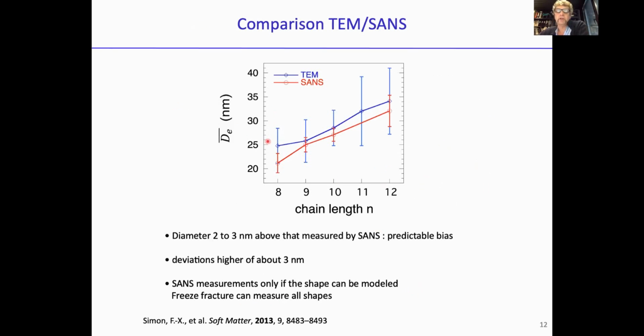So the blue curves represent what I've shown you. These are the diameters as measured by the freeze fracture, and you can see here the polydispersity. And you can see here the real measurements done by small angle neutron scattering. So the first observation that you can make is that the diameter measured by electron microscopy is 2 to 3 nanometers higher than those measured by SANS.